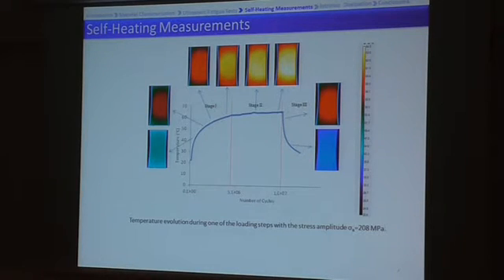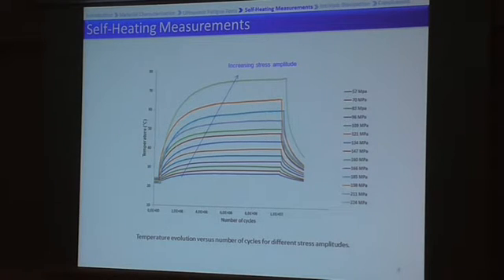And here you can see the temperature fields on the surface of the specimen obtained by infrared thermography. As you can see, the temperature is homogeneous and symmetrical with the maximum value found in the center of the specimen. And here in this picture you can see the temperature increase during cycling for different stress amplitudes. And it's obvious that by increasing the stress amplitude, the steady state temperature has increased.